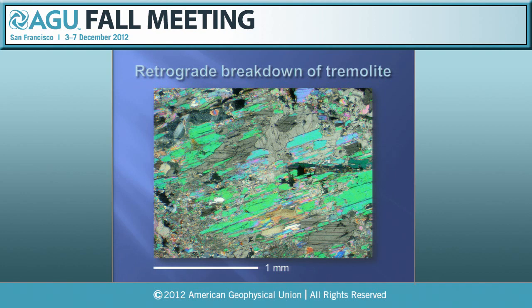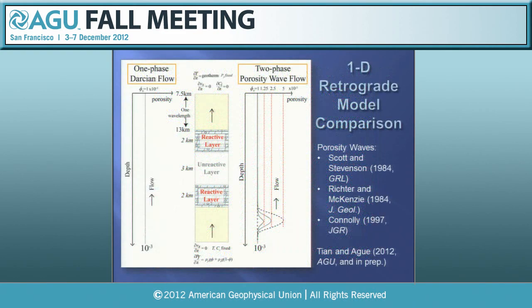So to look at this flow process, we've examined 2 flow end members, with a graduate student, Meng Tian, who had a poster on this earlier in the week. One in which we have a simple model of upward flow in a simple 1-phase Darcian regime. The other is a 2-phase porosity wave flow regime. But in both, what's happening here is that we have an upward migrating fluid that hits a reactive layer that contains that tremolite dolomite assemblage that I just mentioned. Then it goes through an unreactive layer and then back through a reactive layer and then out the top.